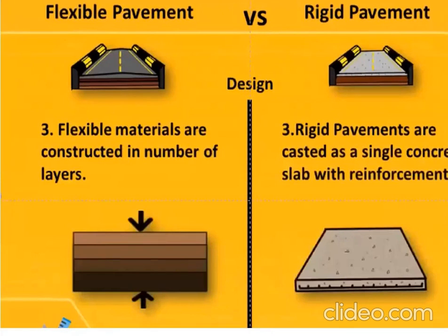Now, the flexible pavements are constructed in a number of layers. Layer 1, you may have a compacted subgrade, then a sub-base layer, then a base layer, then an asphaltic base course layer, and finally an asphalt wearing course. Each cannot be done at one time. Even if you have, say, a 12 inch sub-base, you have to do it in 2 layers to have very good compaction. Conventionally, you cannot compact an aggregate more than 6 inches at one time, right?